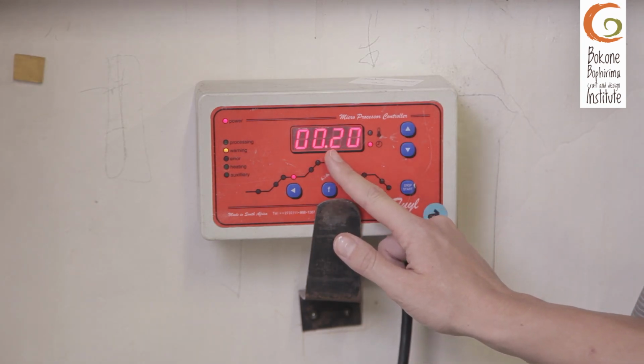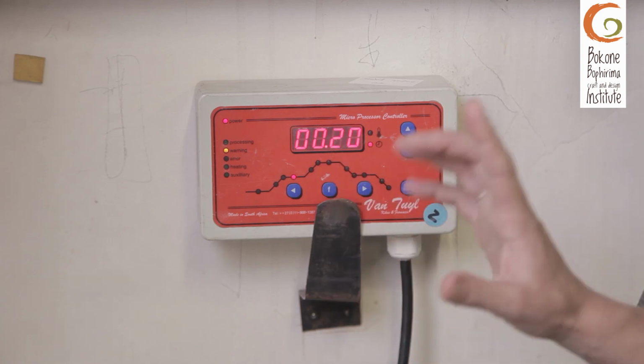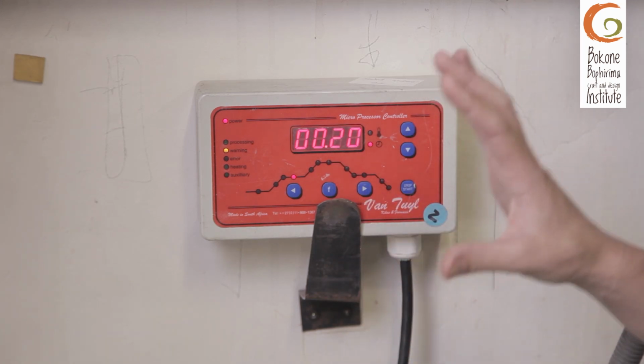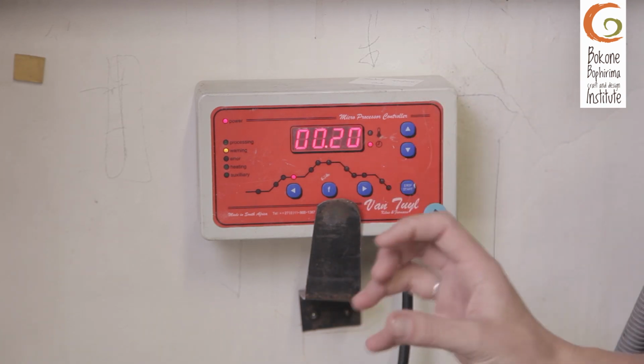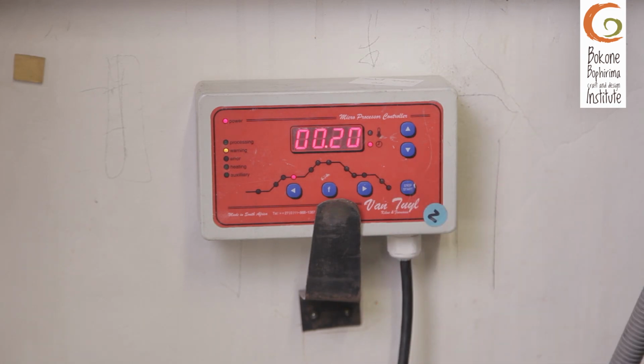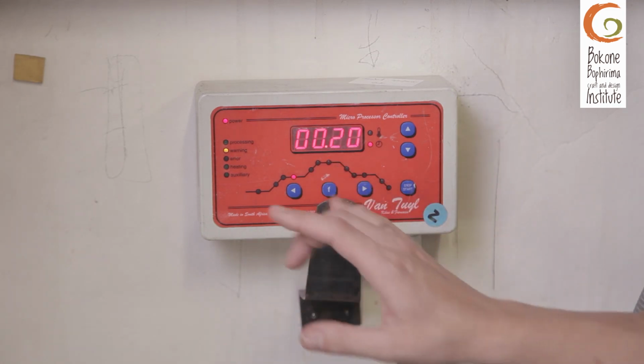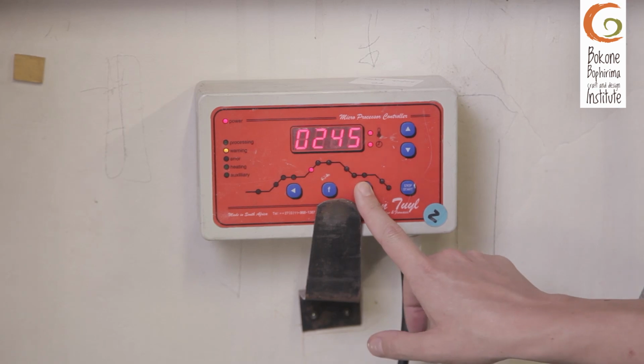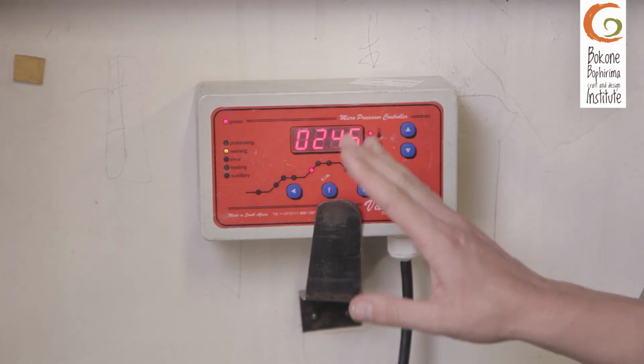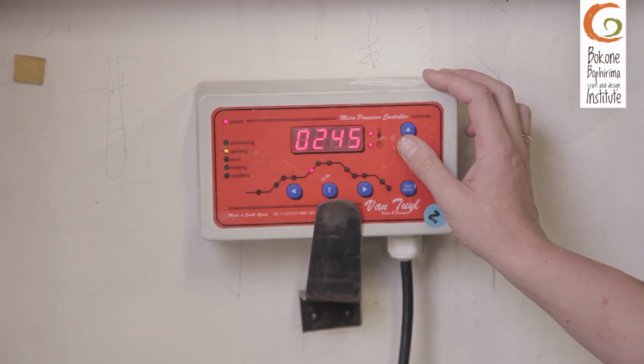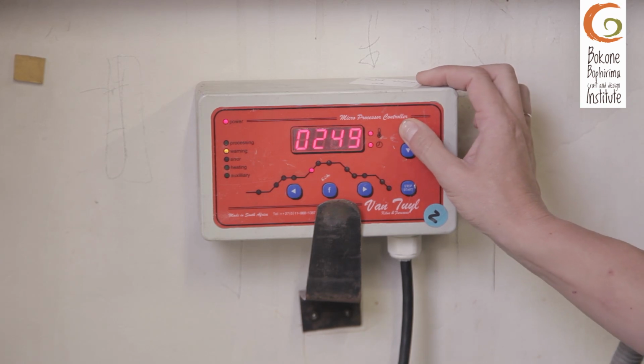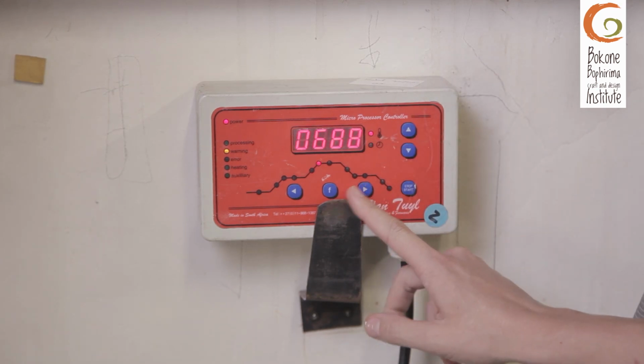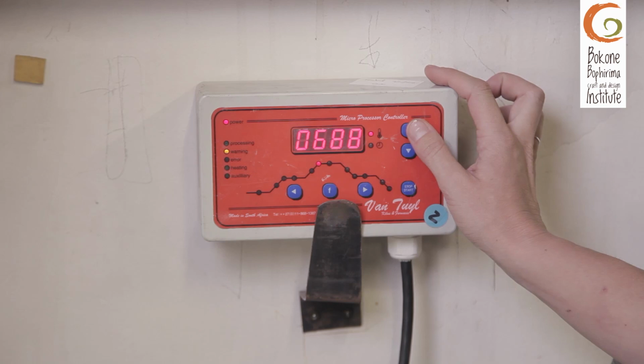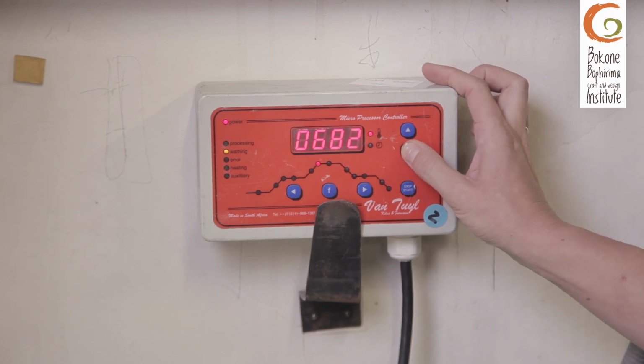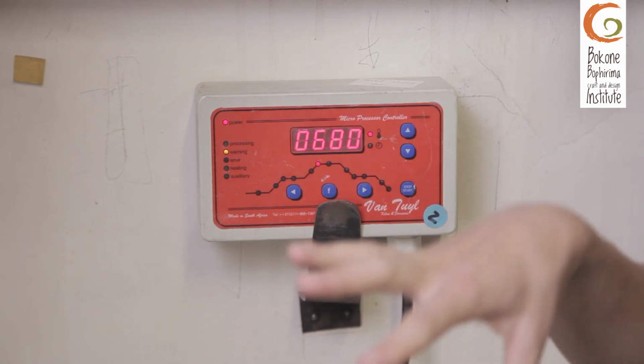I'm holding it for 20 minutes to ensure that my glass is all the same temperature, and not just my glass, I also want to ensure that my mold is also at 580 degrees. We are now ramping up to the top temperature, and I'm going to take it up 250 degrees an hour, up to my top temperature, which is 680. At 680, our glass tends to start to move.